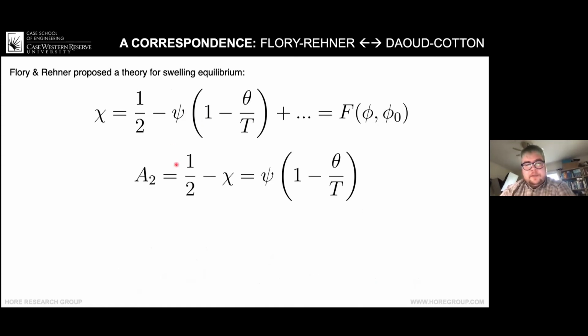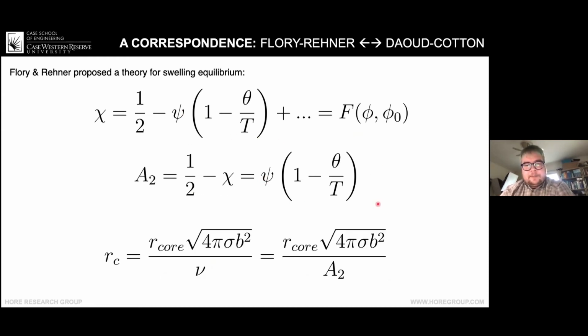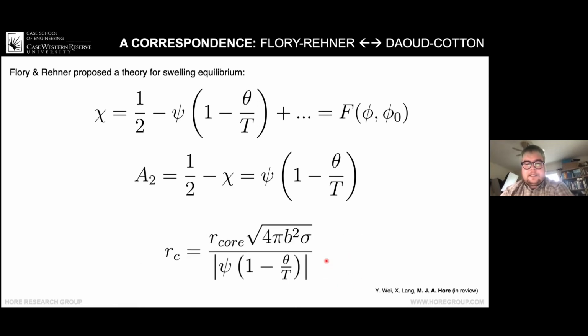And so the dimensionless second virial coefficient is 1/2 minus that. So we get this quantity here. So we're only left with the second term. And we can substitute that in for the second virial coefficient here, and we arrive at this expression. And these absolute value symbols were derived rigorously. So I didn't just put them. There's a process you can go through to get those.